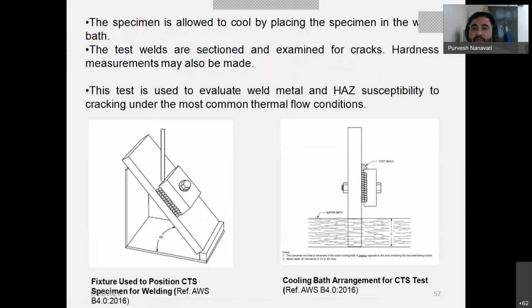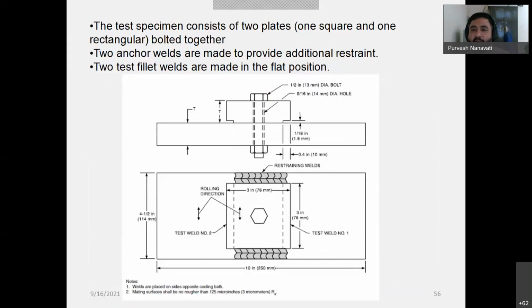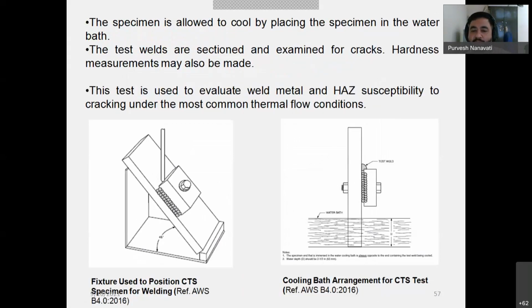Now, what do you do? First, you finish the weld. Now, in a particular fixture, the fixture is just like this. The fixture is at a 45-degree angle, as per AWS B4.0. Most of the time, weldability tests you will find in AWS B4.0. When you finish the weld, you have to put the specimen into the water bath, keeping the weld joint part without touching the water, right?